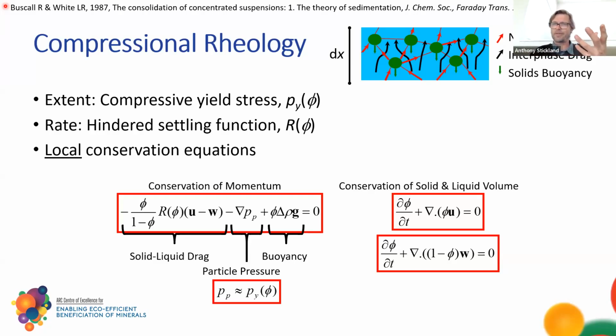But it's a continuum model of behaviour, or phenomenological behaviour. We see these phenomena in terms of pressure dependencies, and so we can write down a continuous equation based on the local volume fraction. We can do a momentum balance and a volume balance over a volume element of suspension, and balance the different forces that are acting on the liquid and solid phases. Once you do that, you end up with a series of local conservation equations. This is the combined conservation equation for the solid and liquid phases.